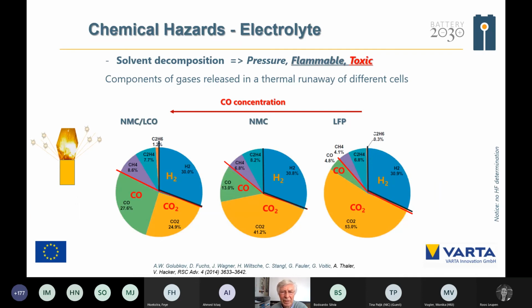So the question about the toxic part of the gases after the explosion, you could see here 3 different chemical systems. The CO concentration for the LFP is about 5%, NMC about 13%, and here NMC and LCO nearly 28% CO. So you have an increase of the concentration of the gases. And we have nearly the same electrolyte. And therefore the question is why we have that increase in the carbon monoxide concentration.